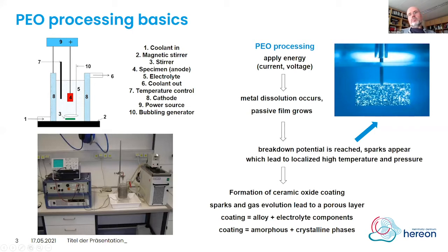If you look basically at the system, you see that you need an electrolyte and you need an anode and a cathode. Your workpiece is the anode, and we basically apply energy, mainly in the form of current or voltage, to the component in the electrolyte, and that drives metal dissolution. And on the surface, a passive film grows, and this gives us a dielectric layer. And as soon as the breakdown potential of the dielectric layer is reached, and that you see nicely on the right, you can get uniform distribution of short-living discharges on the surface of your component. And that gives you high localized temperature and pressure, which is basically responsible for the formation of our ceramic oxide coatings on the surfaces of the light metals.